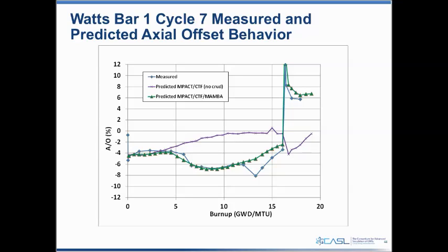Now, this model currently doesn't contain the boron-10 depletion effect in the crud itself. So we don't capture that significant 2% step down at 6,000 megawatt days per ton, or the corresponding one that occurred around 12,000 to 13,000 megawatt days per ton, simply because we haven't included that in the model yet. We intend to, and that's under development, so we'll have that pretty soon as well.